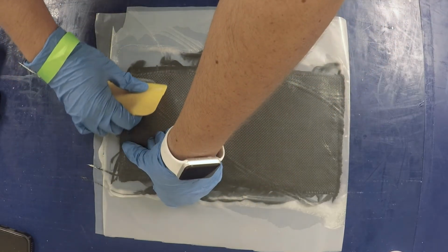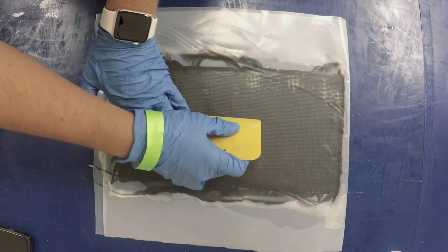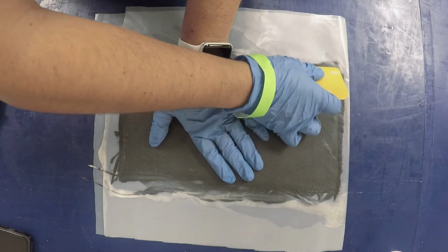After the second layer, be extra careful when pulling the plastic apart, as the topmost layer can adhere to the plastic and peel off your wet laminate.